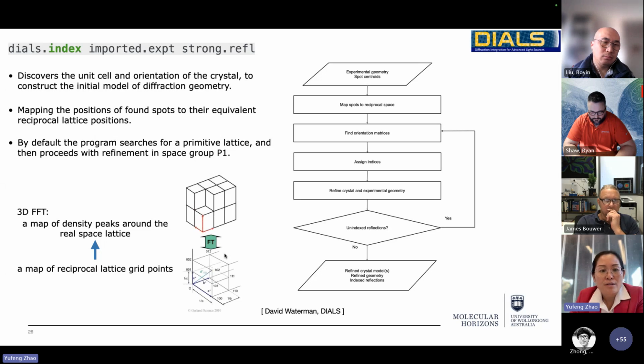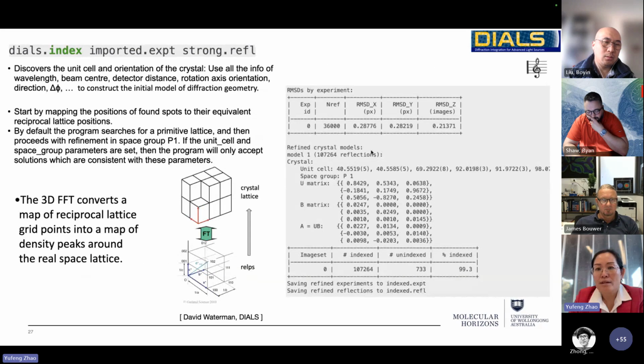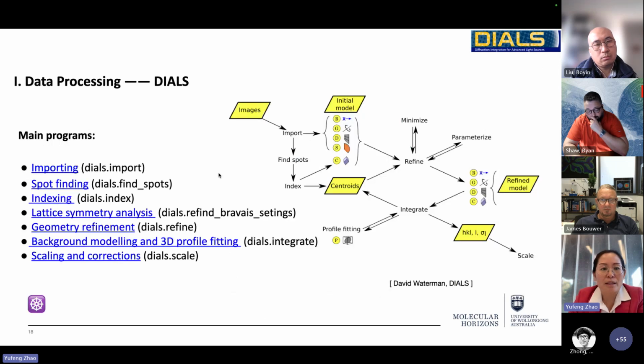And by default, it would do a search for a primitive lattice, starting from space group P1. And after getting the reciprocal lattice points, it does a 3D fast Fourier transform to give us the real space lattice. So you can just repeat until you get really good results you feel satisfied with. Here's what the output looks like. So we will get a space group P1 unit cell and the root mean square deviation and how much you have indexed. So if you are happy, you keep going. Not happy, you can adjust and try to get a better result.